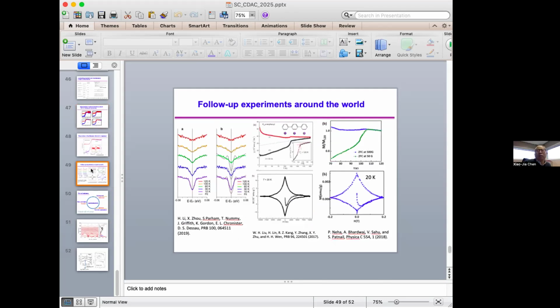They observe a similar thing. I didn't show the resistivity measurement. There's a work from Italy. There are many groups working together. They synthesize the material and measure resistivity for this material. At the same temperature, 120 Kelvin, they indeed observe the resistivity drops substantially, by 3 orders.